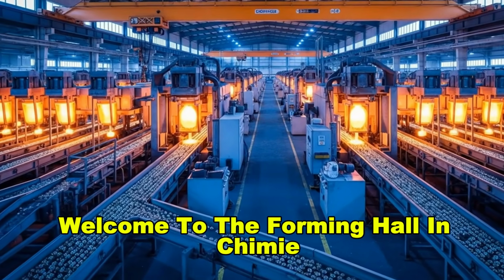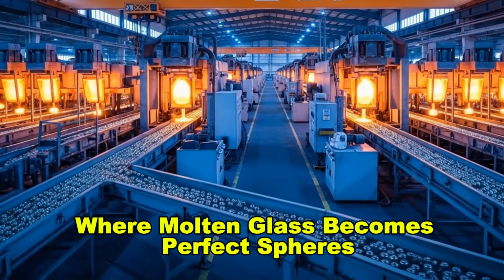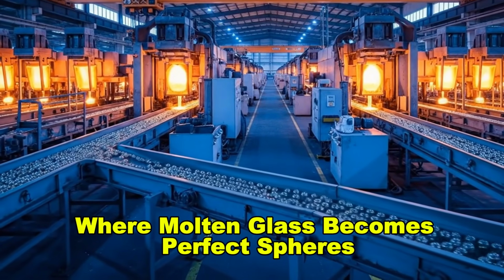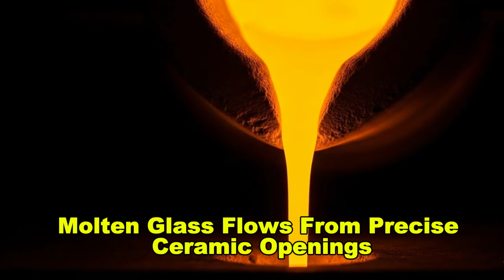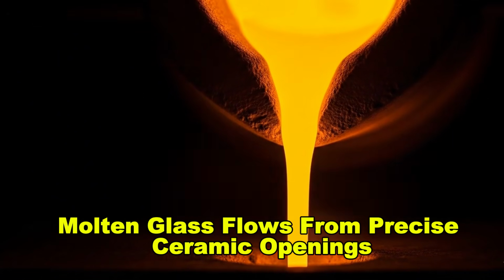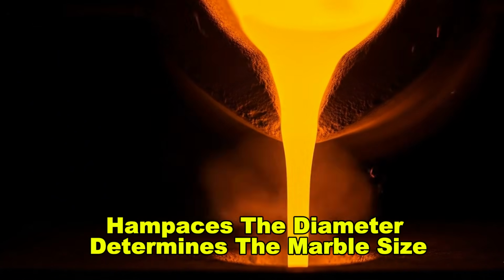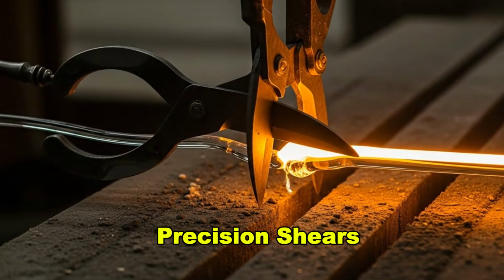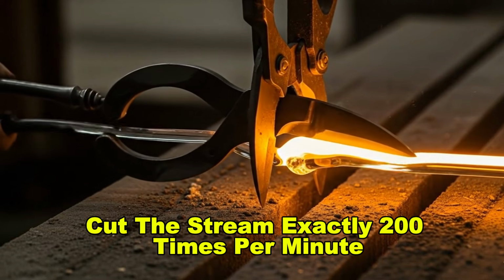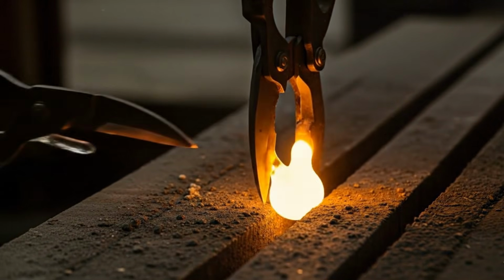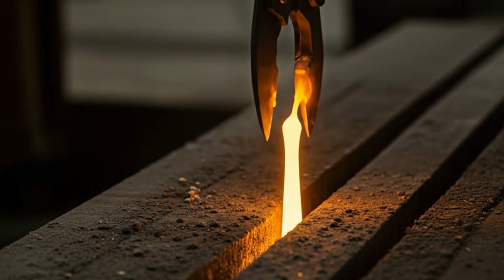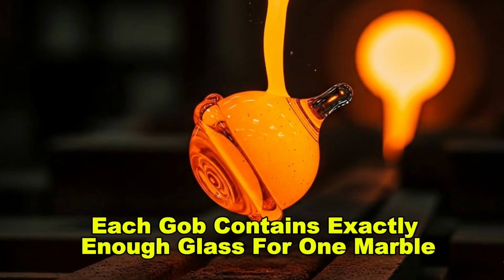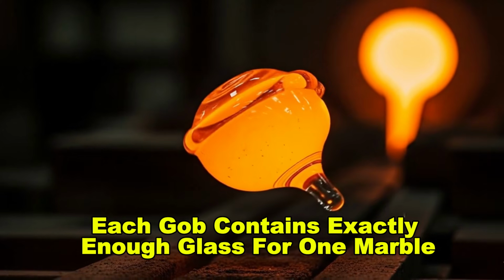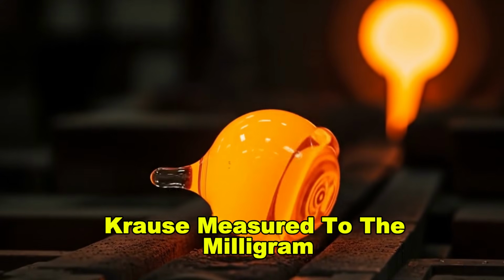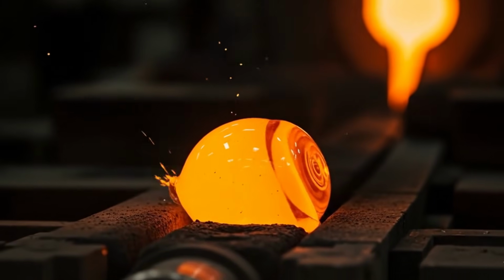Welcome to the forming hall, where molten glass becomes perfect spheres. Molten glass flows from precise ceramic openings. The diameter determines the marble size. Precision shears cut the stream exactly 200 times per minute, perfectly timed. Each gob contains exactly enough glass for one marble, measured to the milligram.